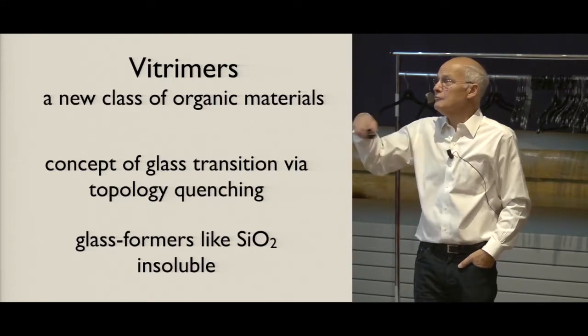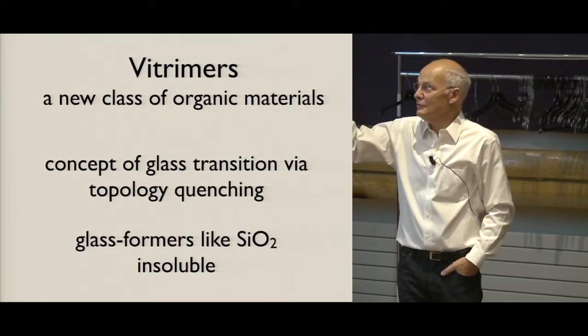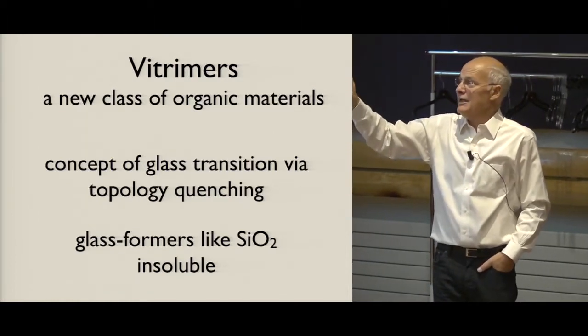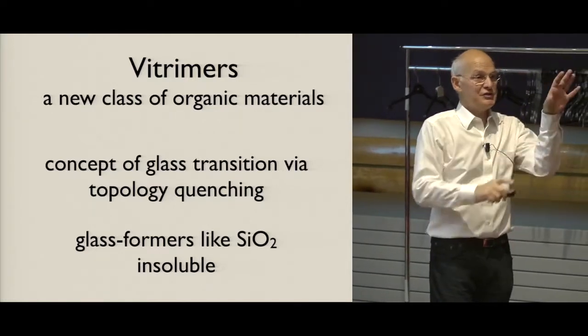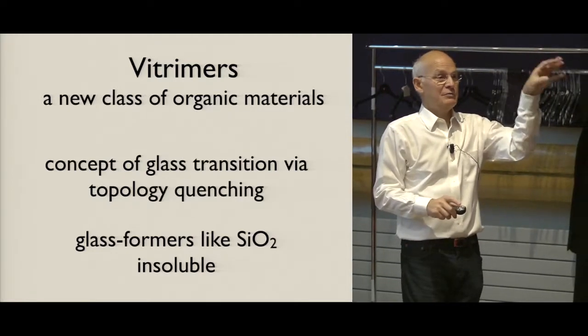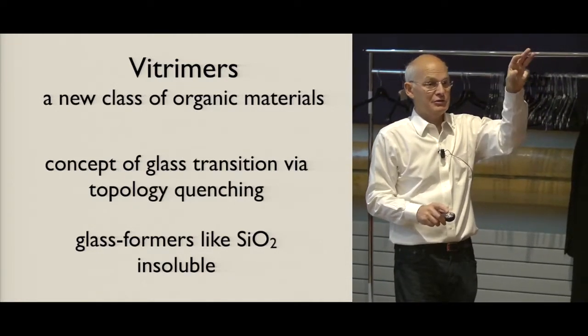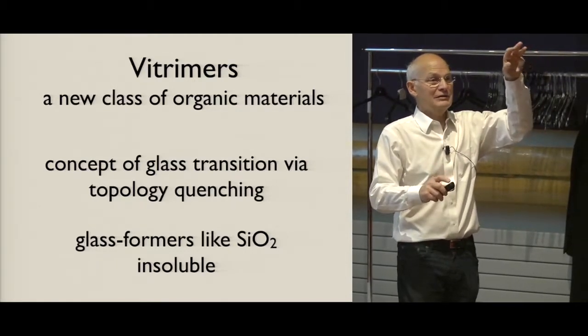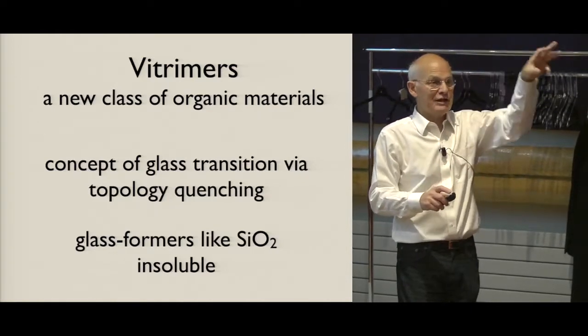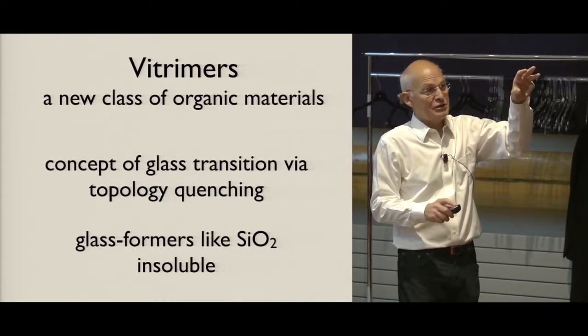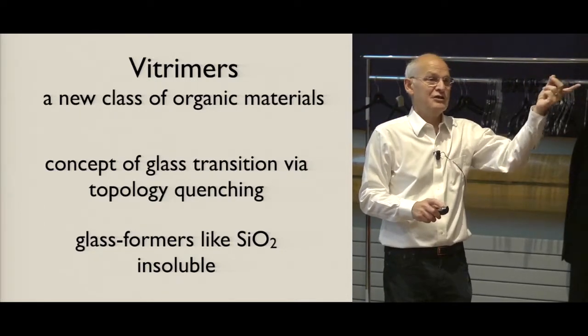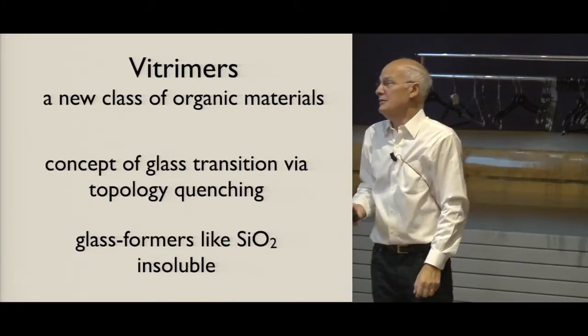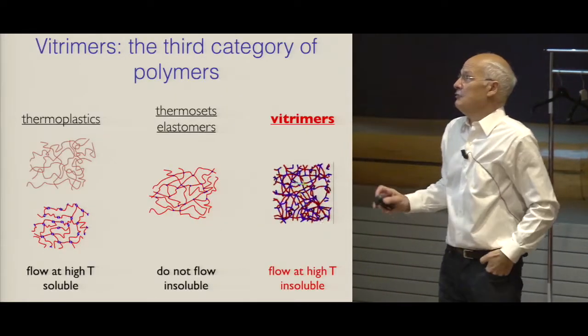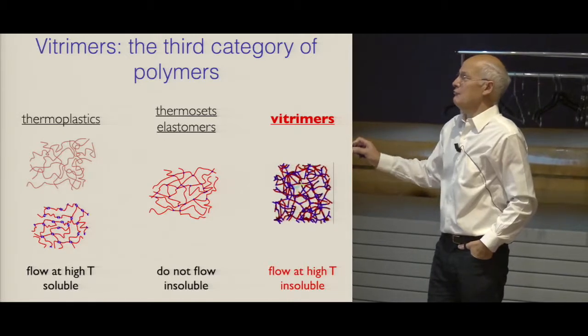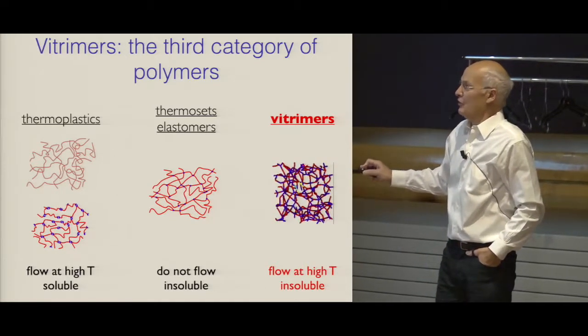And in order to put this concept forward, we said that we can have a glass transition not by changing the density of the system, but by freezing the topology of the network. So rather than having a network, it has a topology which fluctuates without the fluctuation of the number of links and functionality of the network. And so this is a new idea, and it's like silica. Now in terms of polymers, we had thermoplastics and thermosets, and now we have vitrimers, which again flow and are insoluble. So it's a new category of polymers and plastics as well.